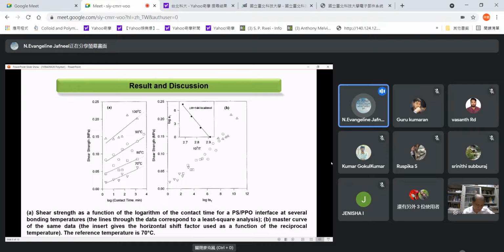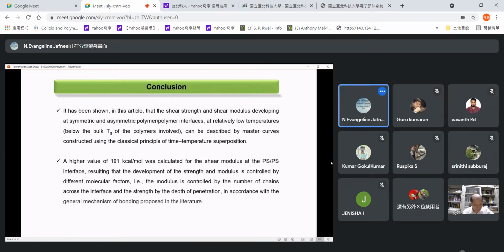The enthalpy of this blend was greater than that of the previous ones. This is because the diffusion of PS chain in less mobile PPO surface requires more energy than the diffusion of PS chain in more mobile PS surface. Thus, we could see the reasonable increase in the enthalpy value.